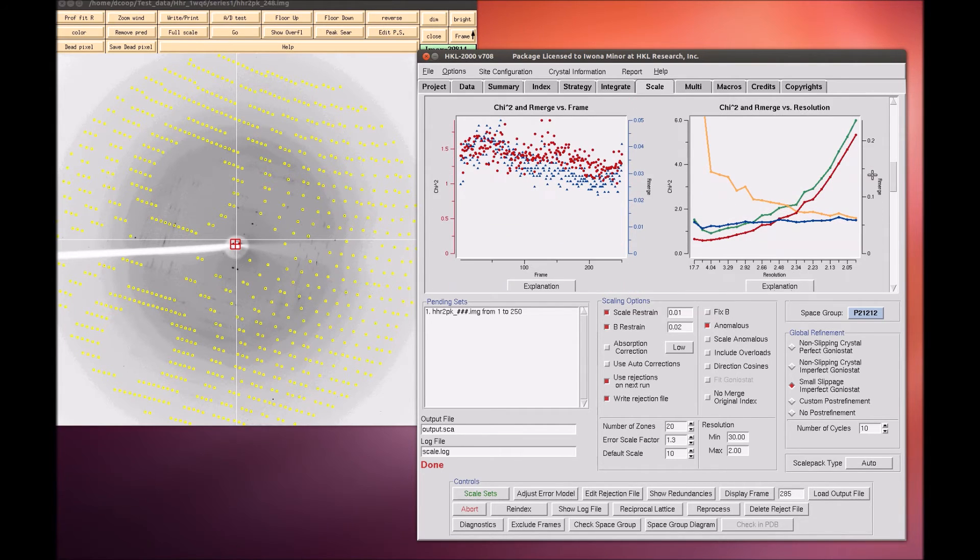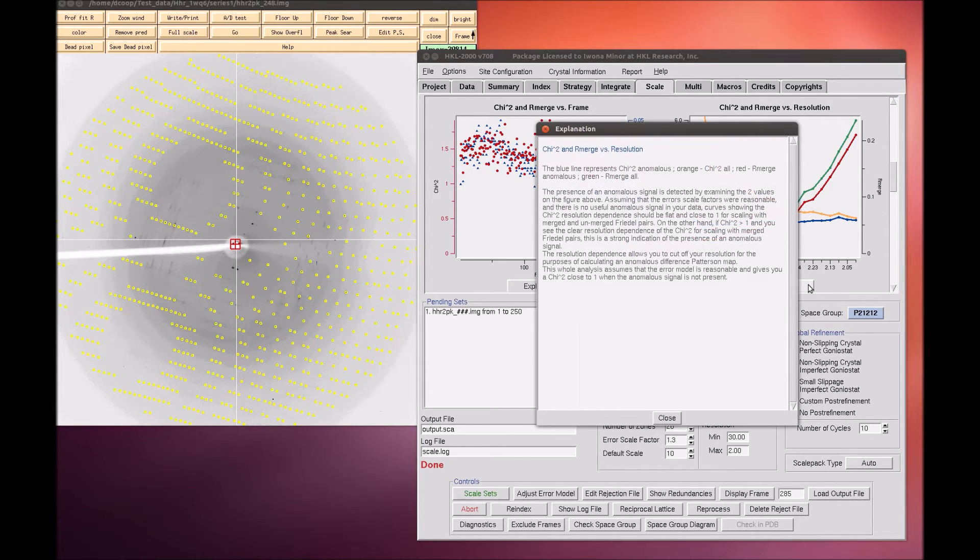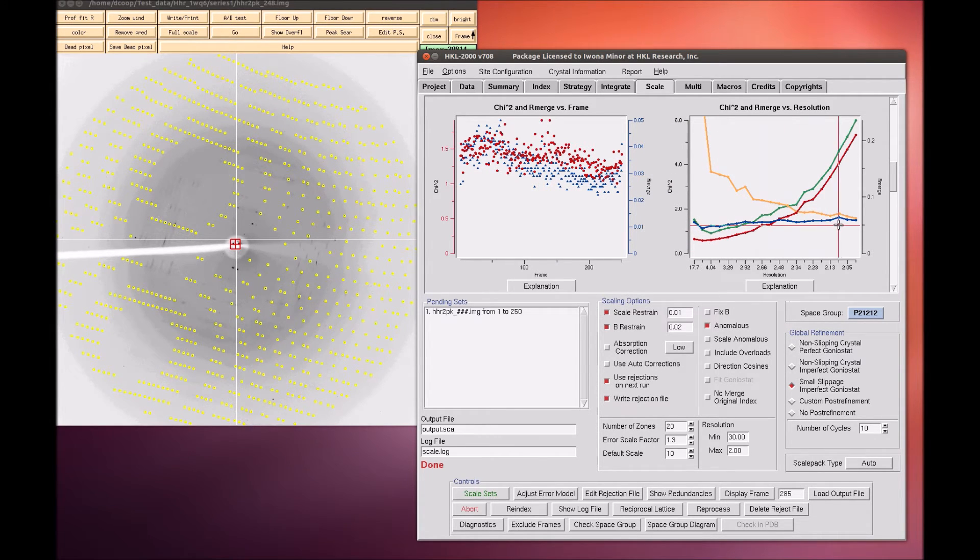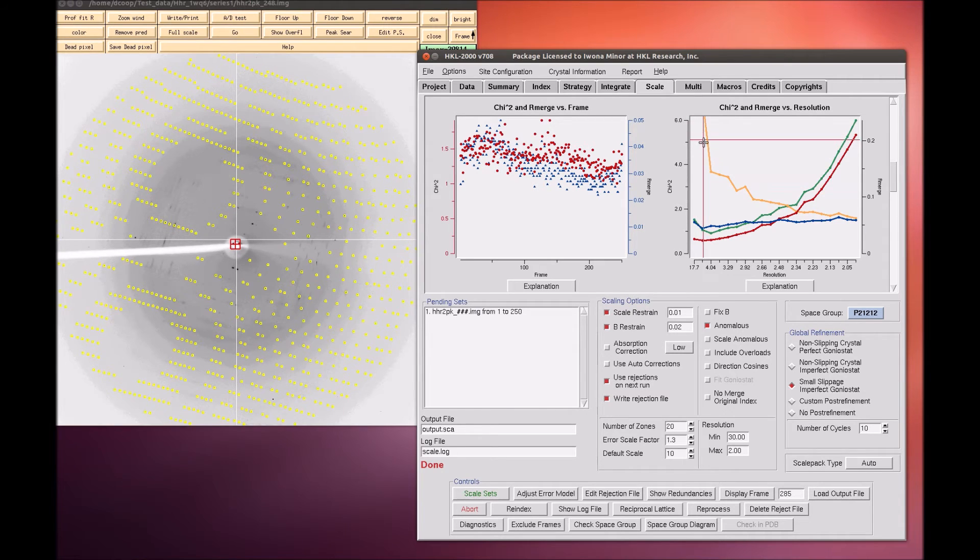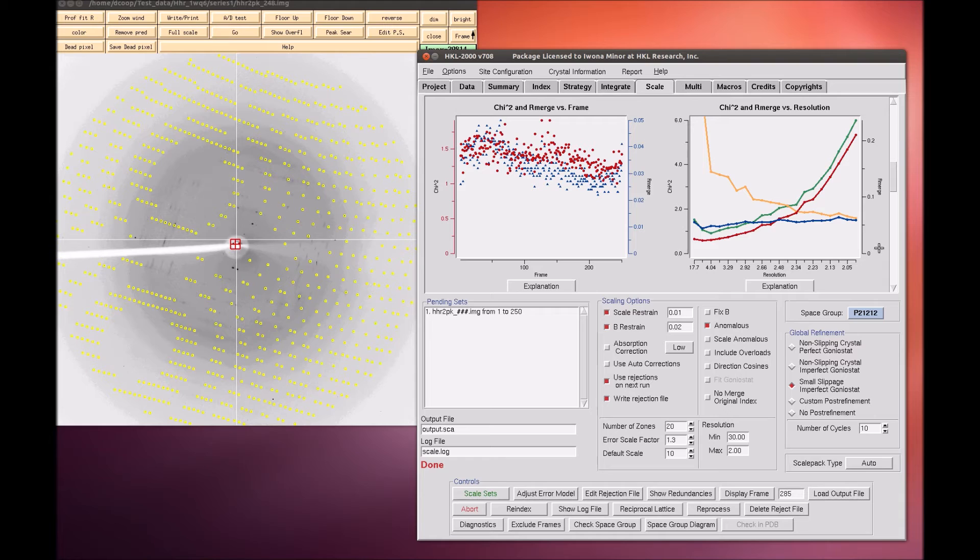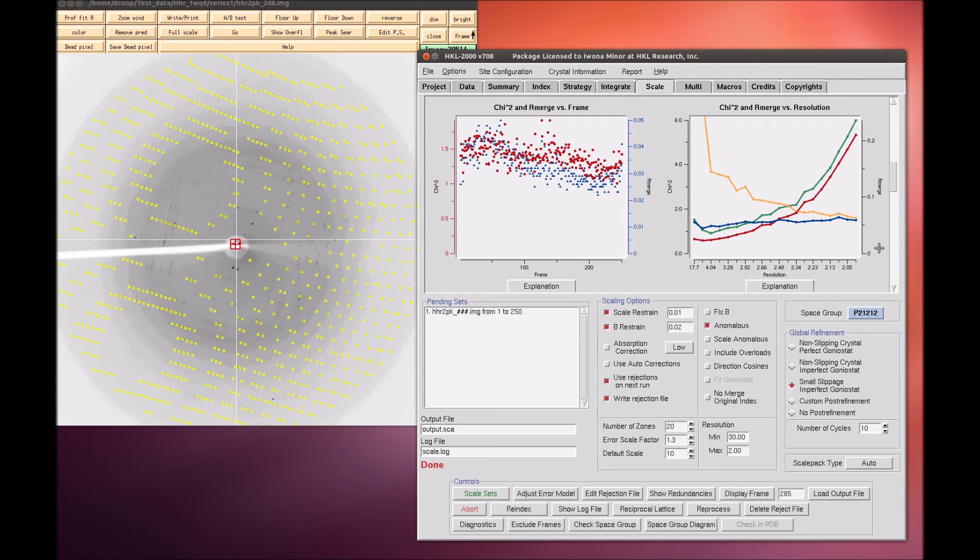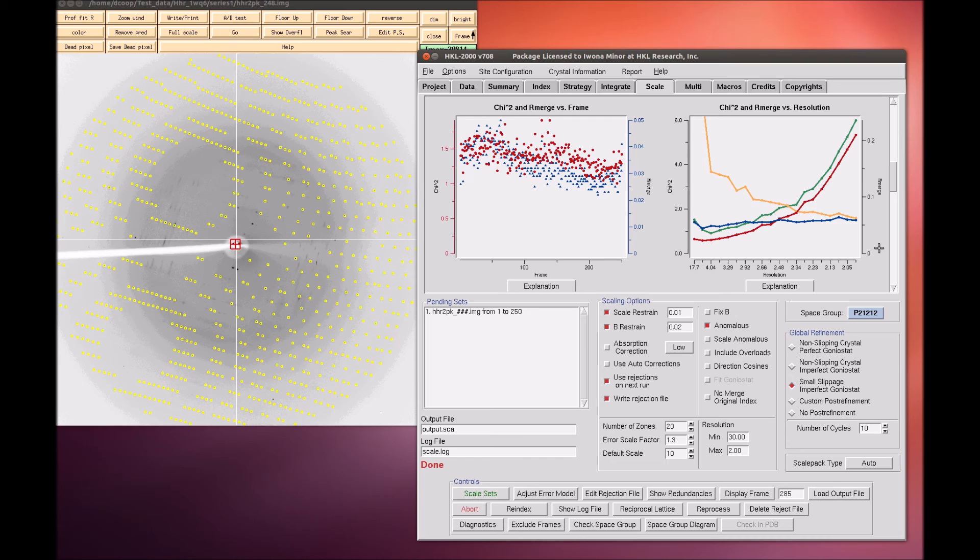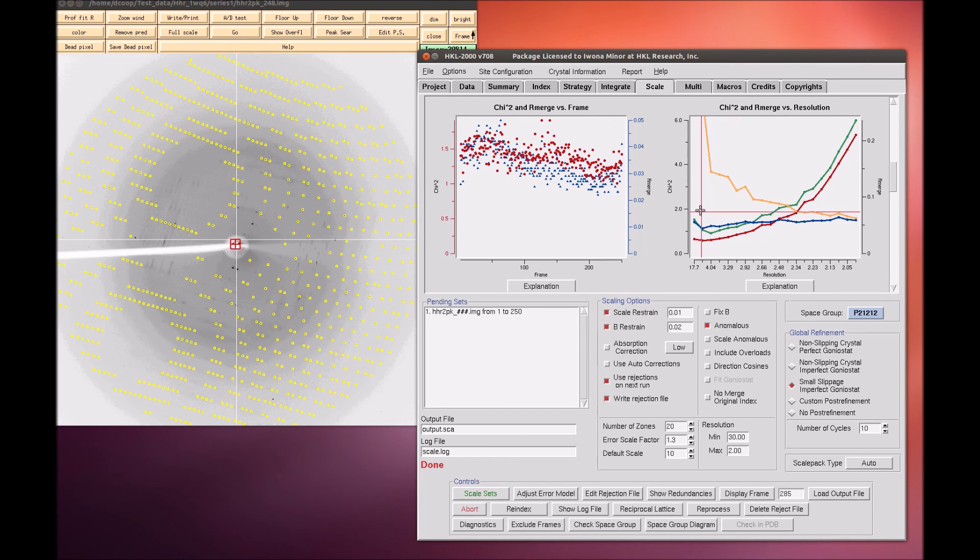You can click on the Explanation button under each graph to see what each line represents. In the graph of chi-square versus resolution, the blue line represents the chi-square values when Friedel pairs are kept separate, and the orange line represents the chi-squared values if the Friedel pairs are merged. The fact that the chi-squares are higher when they are merged indicates that there is a measurable difference between Friedel pairs, which indicates an anomalous signal. This example has one of the strongest anomalous signals you may ever see. You can usually solve the structure if there is even a modest difference between these two lines at the lower resolutions.